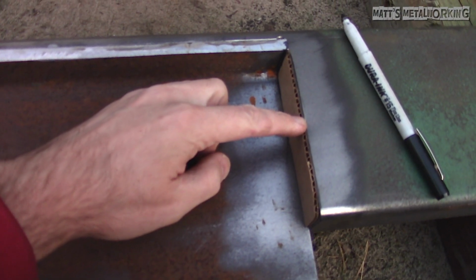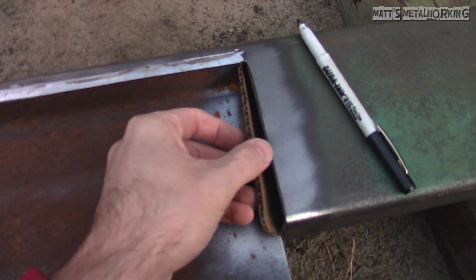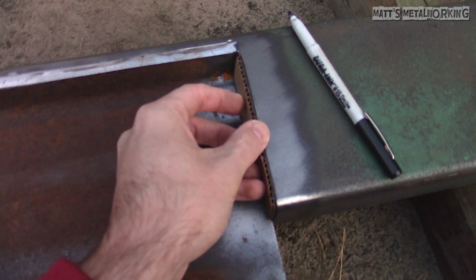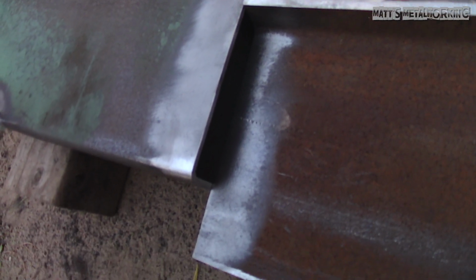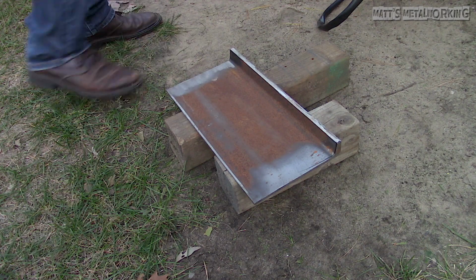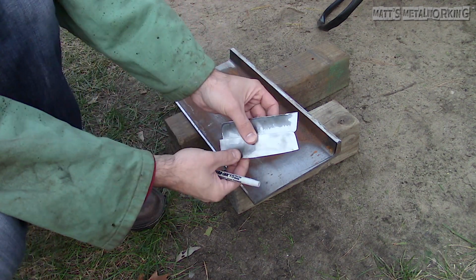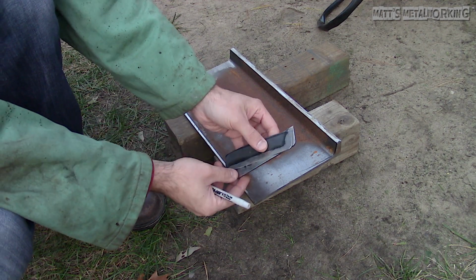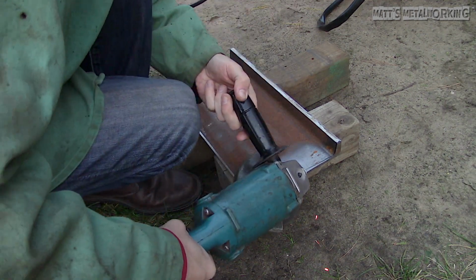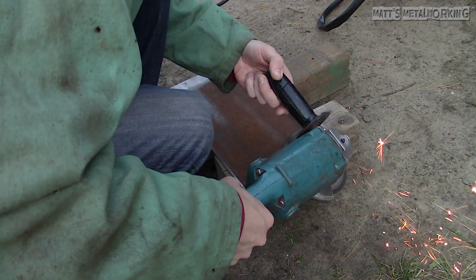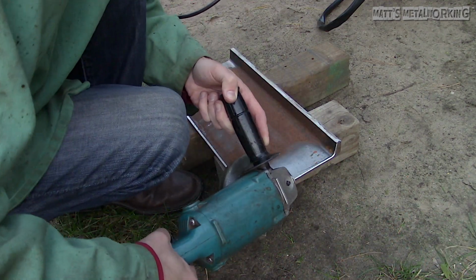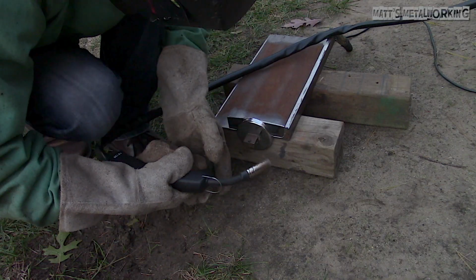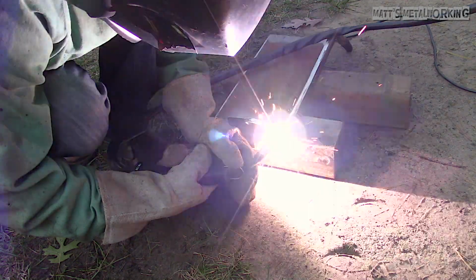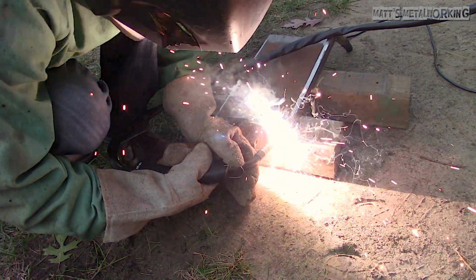I have already cut the filler plates to size and used the section that was cut out from the tubing for the license plate area. I didn't cut the outer edges to size as they can be ground down after once it's tacked into place. The plates will be solid welded on the back side so I can maintain clean corners on the outside. I did chamfer the edge of the channel to help with penetration. The plates were also cleaned up to remove any mill scale. A magnet was used to hold the position of the plates, and they were tacked into place.